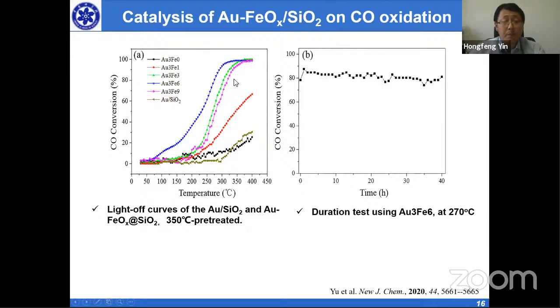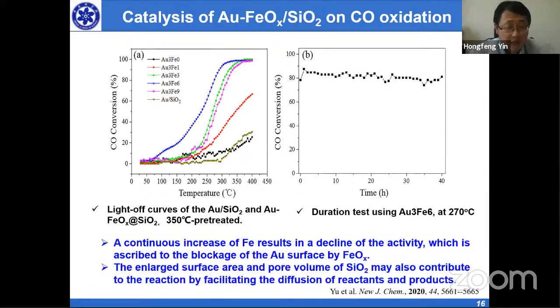It will reach the peak when the ratio of gold to iron is 1:2. With more iron introduced, the activity will reduce. When we pick the ratio of gold to iron of 1:2, the catalytic activity is pretty stable. We can see that at 270 degrees Celsius over 40 hours, there's no degradation. So that's what we see for the gold iron with silica as the shell nanoparticles.